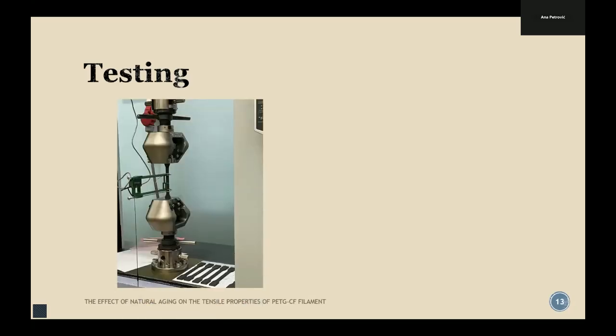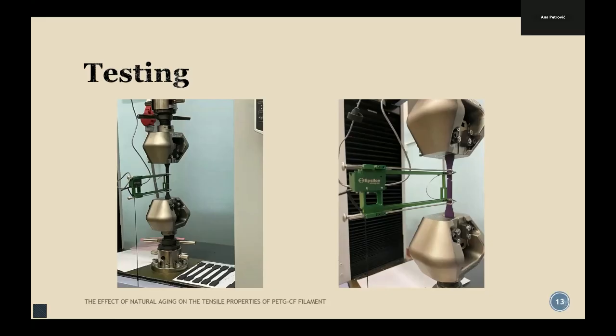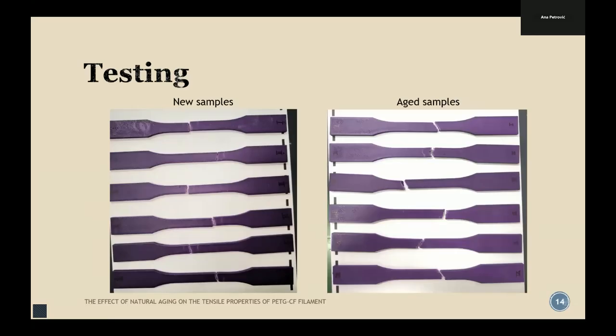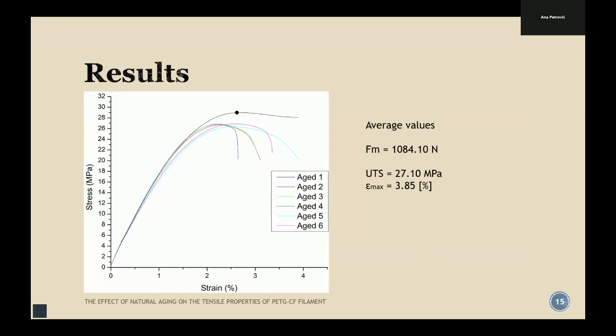This is the setup of the experiment, and this is the close-up, so that we can see the extensometer of 50 millimeter gauge length and the machine on which the test was performed. After the testing, we get these types of fractures for the new samples and for the aged samples. From this picture you can't see much, but we can see that in new samples we have deformation stripes on many samples, while on aged ones we only have them on one, only for 4 samples.